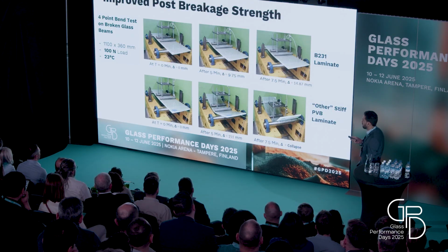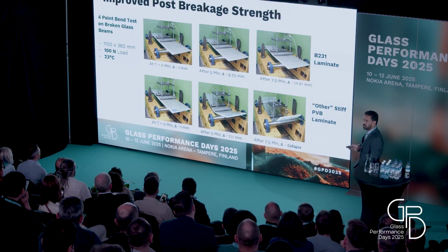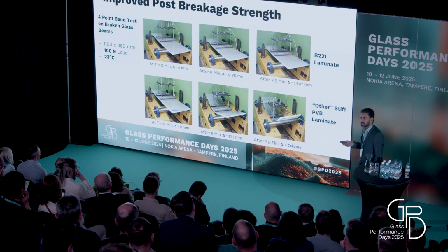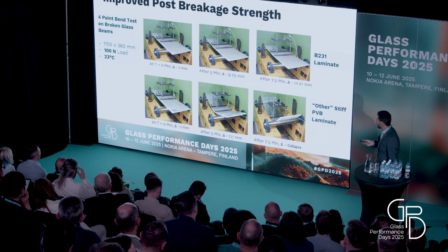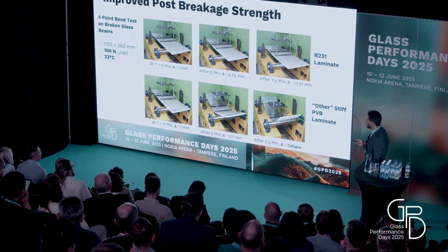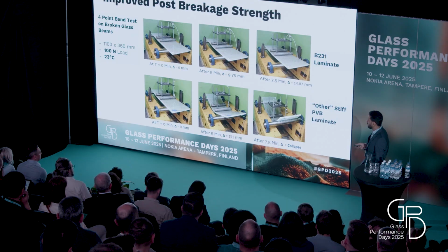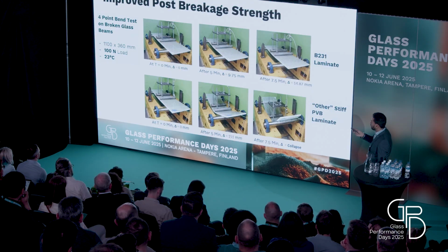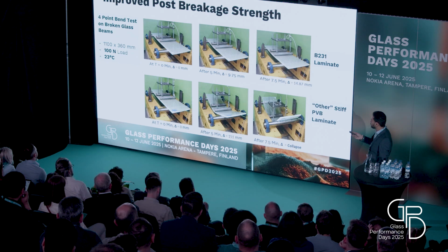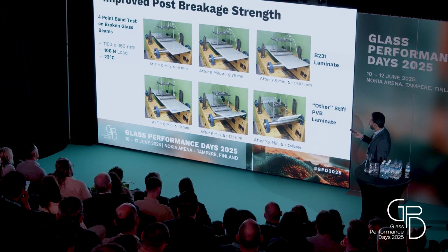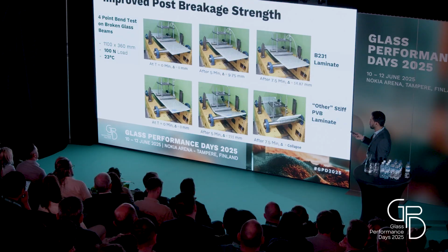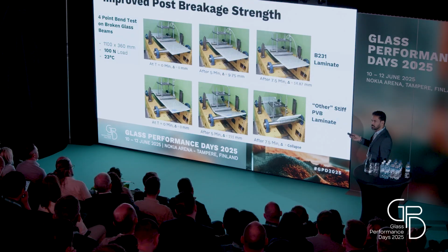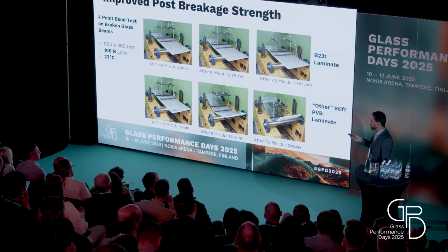This is the 4-point bend test arrangement, which has been placed in a temperature-controlled environment. The temperature was 23 degrees centigrade, room temperature conditions. After the application of the load, you can see the load is not increasing, but the creep is coming into the picture. The deflections at the center of the beam are increasing.